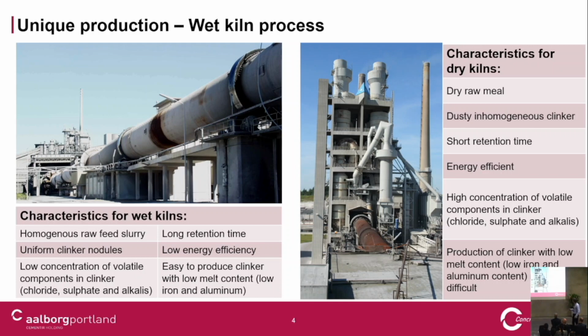But one of the advantages of our wet kiln is that the clinker coming out is more pure. We have a lot of the volatiles in our raw material - the alkali, the sulfate, and the chloride - evaporated in the long kiln and goes out with the flue gas. So what is left in the clinker is lower alkali, lower chloride, lower sulfate content. Whereas in the dry process, where we have circulation and cyclones bringing back material interacting with the flue gas, there we have a high concentration of those volatiles, which influences what is in the clinker - higher alkali, higher chloride, higher sulfate.